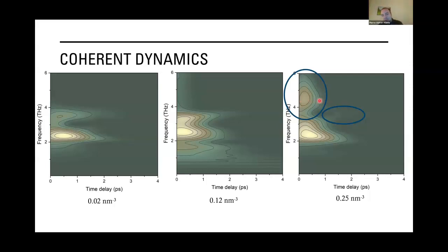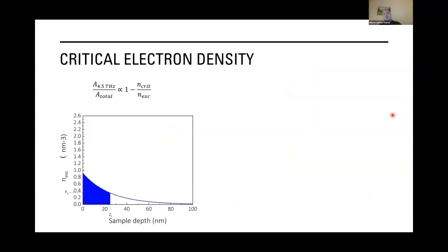So if the vibration of the amplitude mode is a signature of the phase of the material, we have here a change of this vibration spectrum, which indicates a change of phase and the existence of a metastable phase that disappears in a 1 picosecond time scale. And what is interesting here is, what is the origin of this phase transition? Namely, is it a thermally induced transition, or is it some type of photodoping effect?